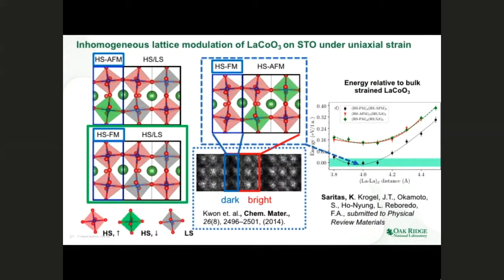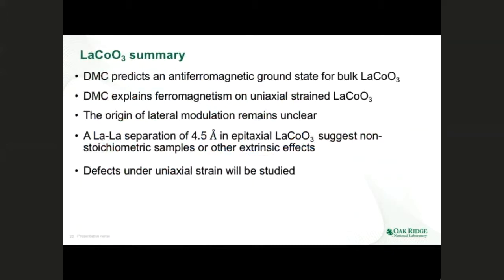So we are doing further investigations on how defects may change this structure. Maybe that could be other defects such as lanthanum antisites or cobalt antisites, which may change their locations during this process and may give rise to the much larger lattice modulations that are observed in the experiments. So the summary of this part is that from fixed node diffusion Monte Carlo, an antiferromagnetic ground state is found for lanthanum cobaltite, and DMC explains the ferromagnetism in the axially strained lanthanum cobaltite, but it is not able to explain the large lateral modulations, which are nearly 4.5 angstroms in the experiments, and we are in the process of studying the defects.